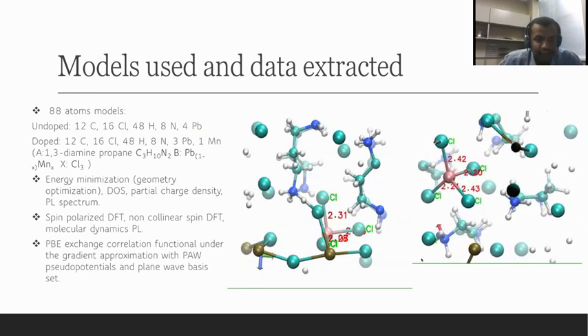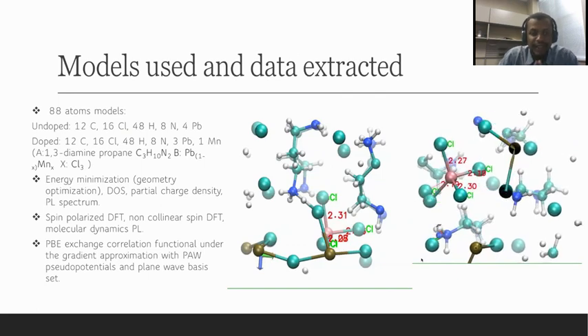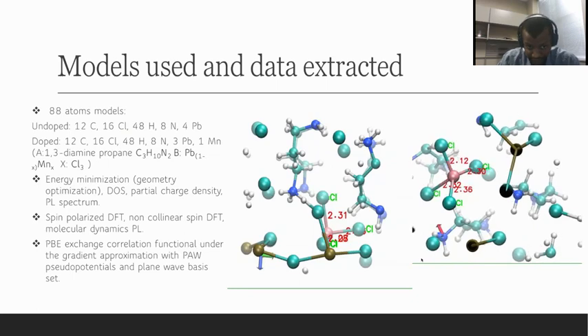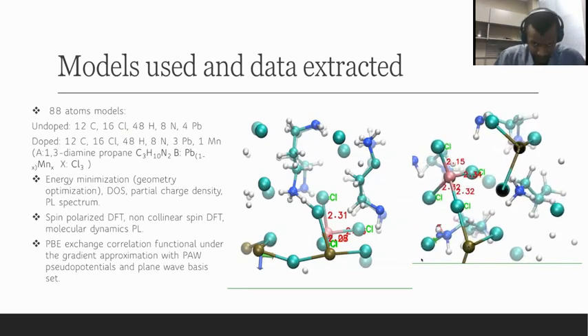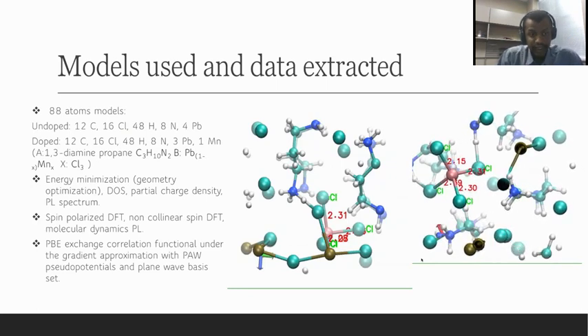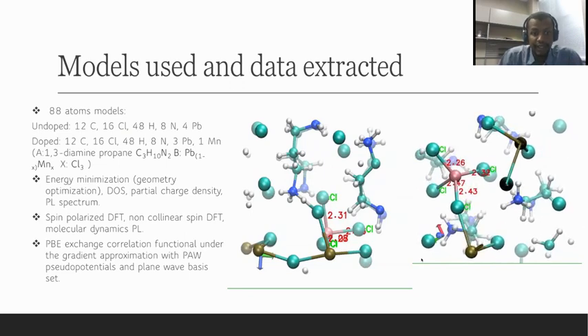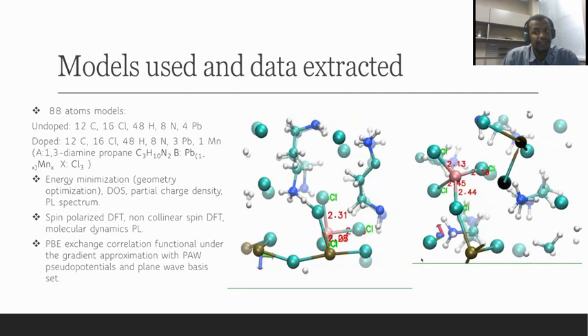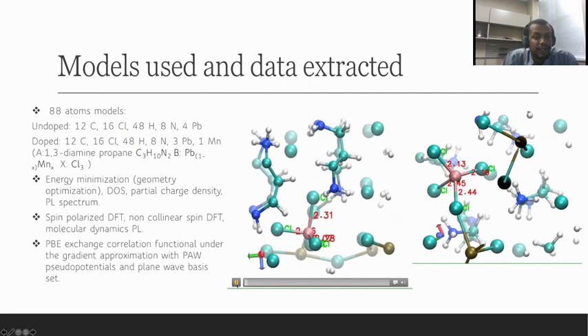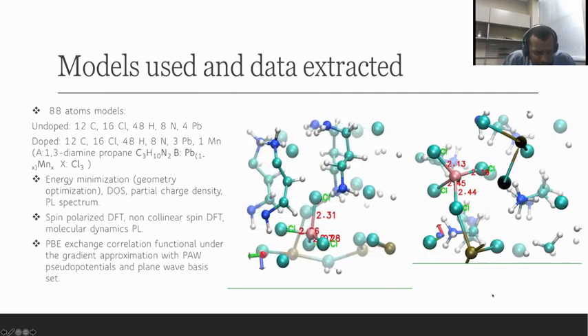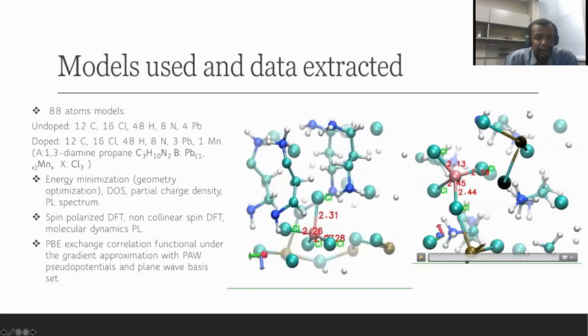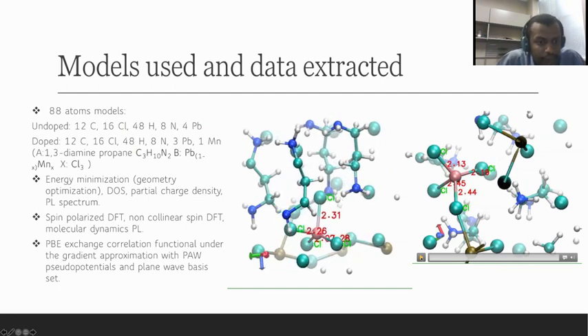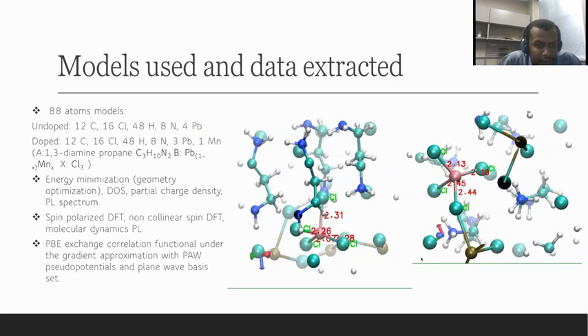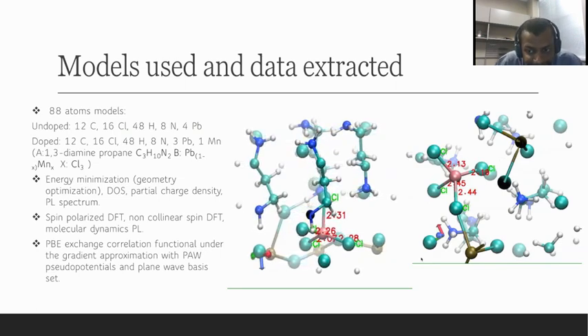And so the data that was extracted were energy minimization, the density of states, partial charge densities, and the PL spectrum for the doped model, using spin-polarized density functional theory and non-collinear spin density functional theory. Also the molecular dynamics PL spectrum was plotted for the doped model as well. The PBE exchange correlation functional was used with the PAW pseudopotentials and a plane wave basis set. Next slide, please.